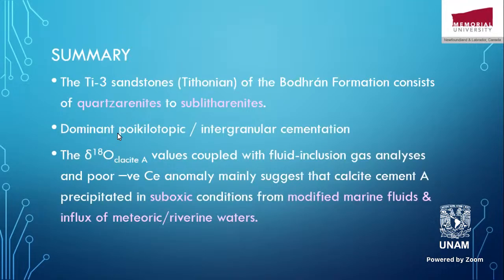In summary, the sandstone unit, it's called TI3, that was Tithonian of the Bodran formation, consists of quartzarenites and sublitharenites, dominant intergranular cementation. Delta O18 of the intergranular cement, coupled with the fluid inclusions gas analysis, and the poor negative cerium anomaly may suggest that the calcite cement may be precipitated in suboxic conditions from modified marine fluids, with influx of meteoric water and riverine water.